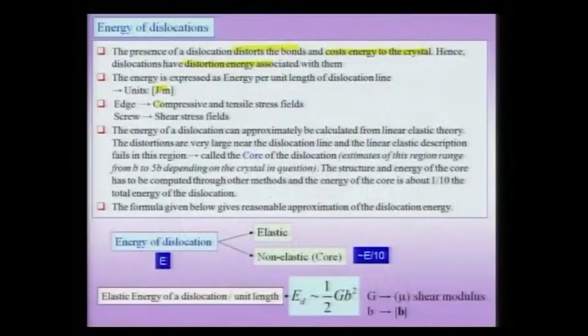Now, there is a fundamental difference between the edge and the screw dislocation in terms of their stress fields, and we will soon see the kind of stress fields they are associated with. The edge dislocation is associated with compressive stress and tensile stress fields, while screw dislocations are associated only with shear stress fields. And therefore, the energy associated with the edge or a screw is also different,